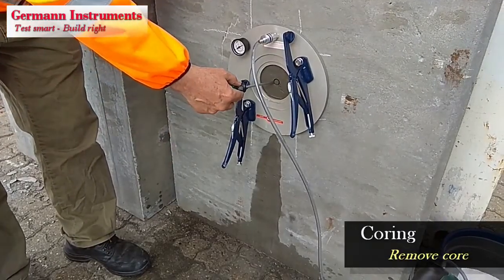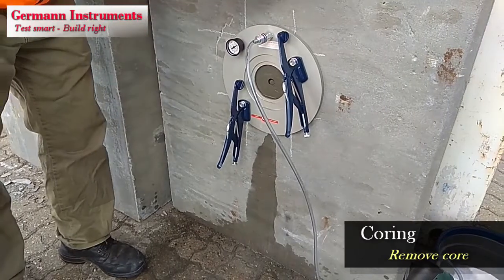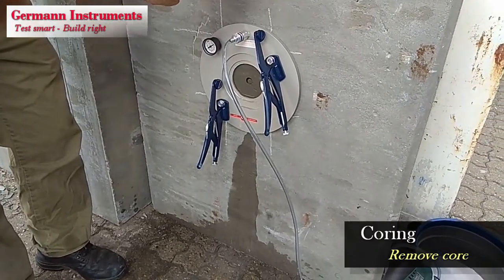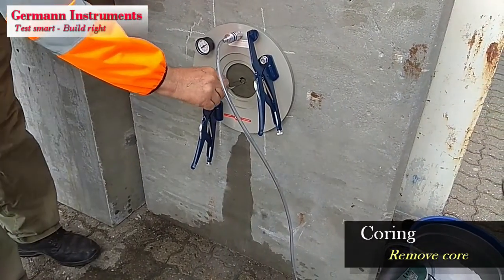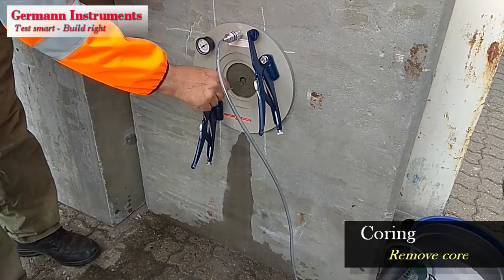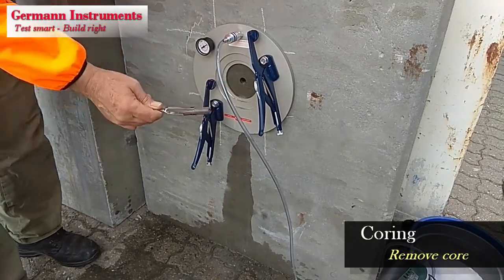Break the core with a screwdriver and remove it with a tweezer. The core is excellent for testing the depth of carbonation, for example by spraying its surface with the rainbow indicator or the deep purple indicator.